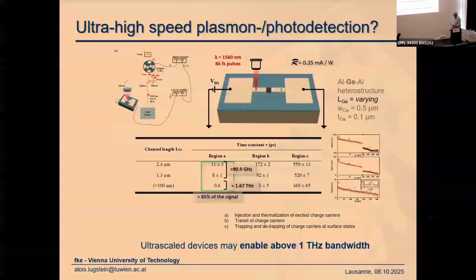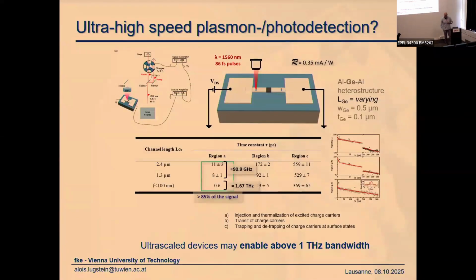We did the same cross-correlation measurements to get an idea about the temporal behavior of this device, about the speed of the device, and we investigated 3 different devices with 3 different channel lengths, a rather long device, 2.4 microns, 1.3 micron, and one less than 100 nanometer. And in the cross-correlation signal, we have 3 different regimes with 3 different slopes, which corresponds to 3 different time constants. We have a very fast process with a few picoseconds time scale.